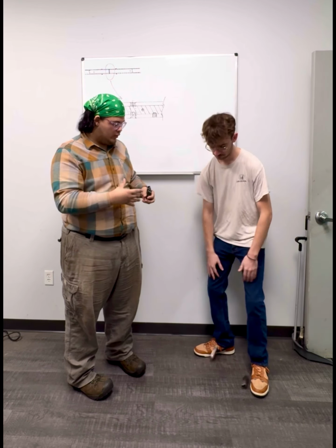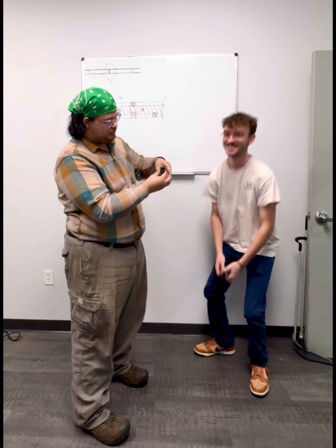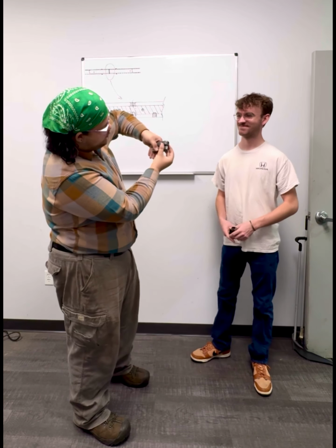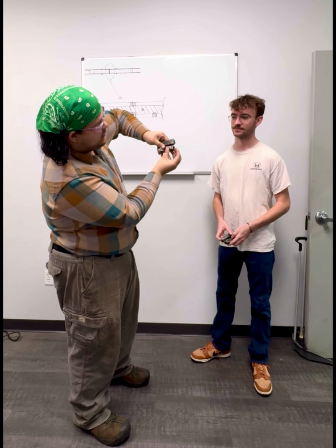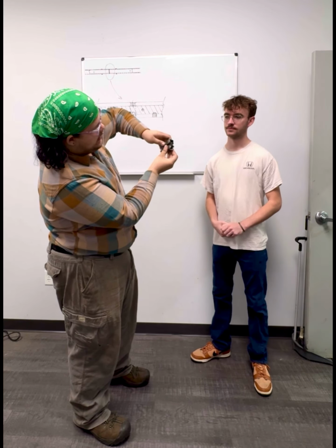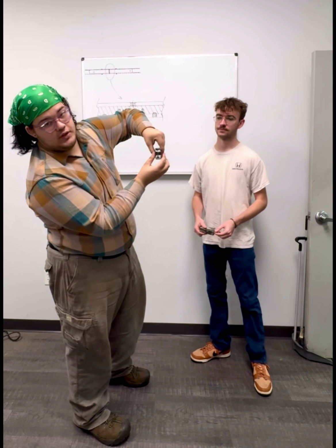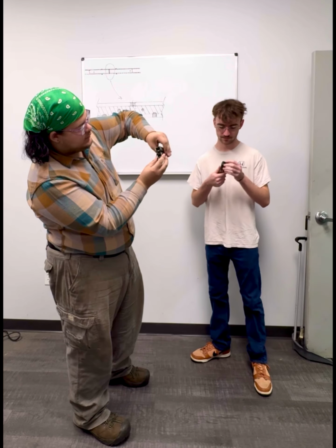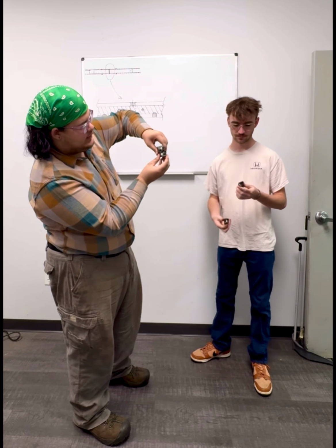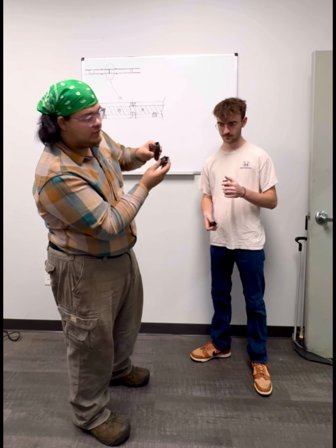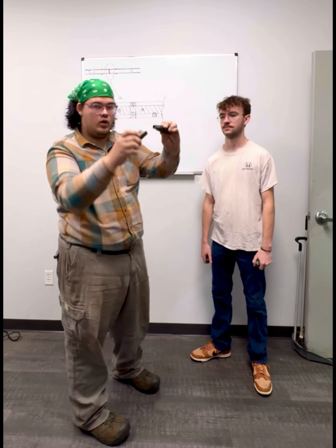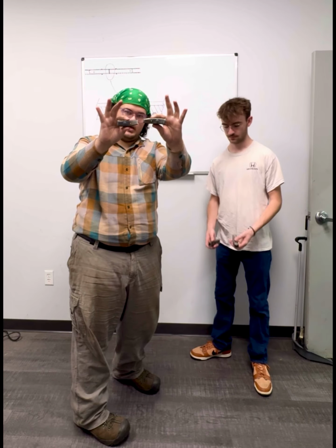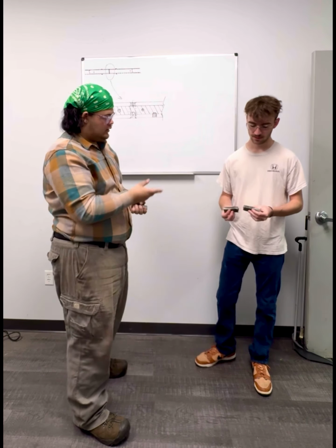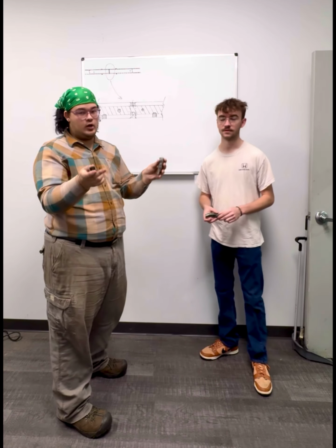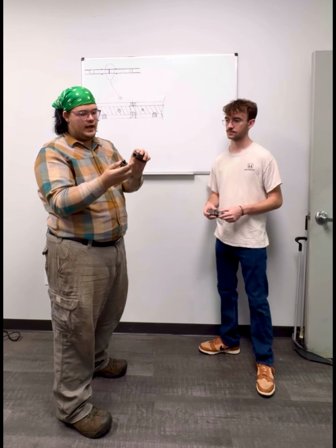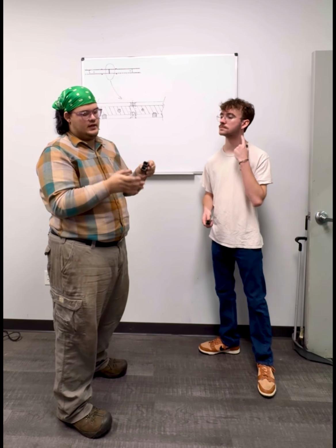As you saw in the video, for the full penetration tubing, the tubing broke just at the edge of the weld. And the heat affected zone is most likely the cause of that. The spot welds held up well. The weld is still tied into the inner tube, and it took roughly 3 bends and pretty heavily deformed the ends of the exterior tube in order to break this. And none of the plug welds broke. The actual weld did not break either. It was just the metal right at the edge of the heat affected zone.